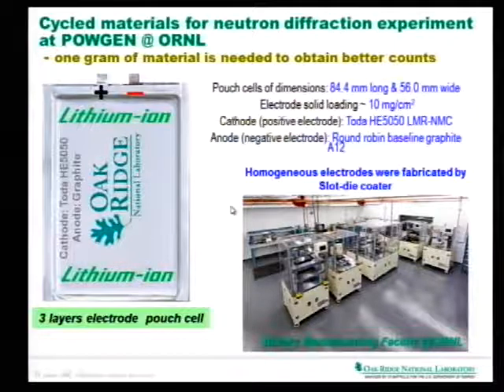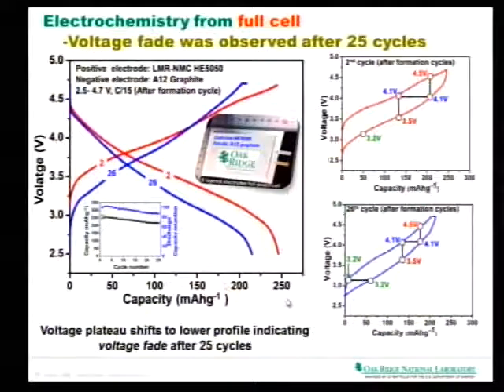That results in something like, what is it, Debashish, 120 coin cells? So 120 coin cells per sample. That's just unsustainable. You can't do that. And there's where we were fortunately able to create large pouch cells, cycle that material in that more or less industrial size, create enough material of that experimental stuff, and do that characterization. And what we're then able to do is we look into the details of, okay, if we start cycling this material over long periods of time, what is happening?